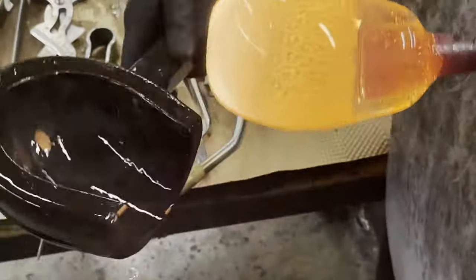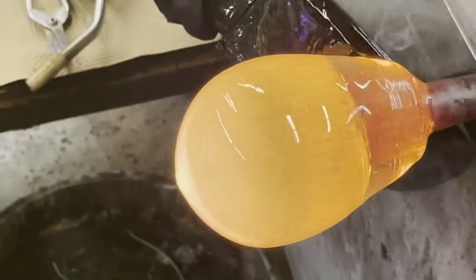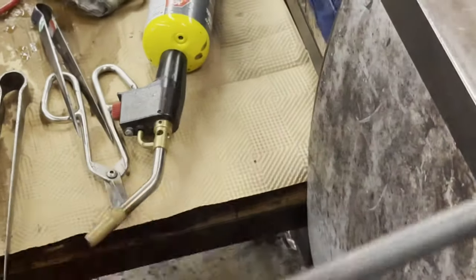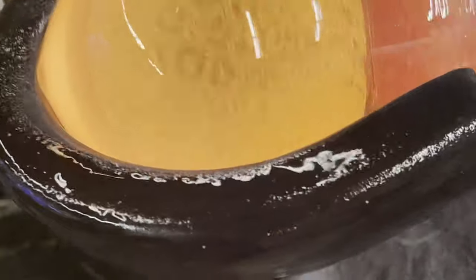The wooden block is our best friend. There's always a wooden block large enough to accommodate its size. This block will distribute the heat and the glass around a distorted bubble. A good rule of thumb is to always block at least two times before you introduce air — this again evens out the temperatures.